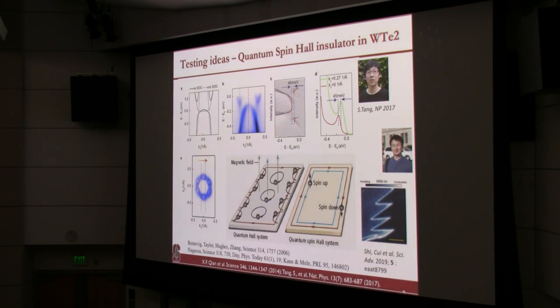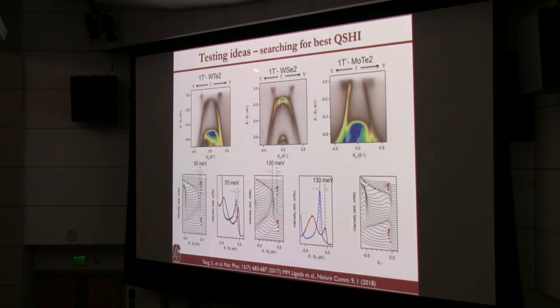Okay. Now, you can also use this spectroscopy to optimize the material. Tungsten ditelluride is a subject being studied a lot. Okay, but if you really look at the system systematically, instead of tungsten ditelluride, you can look at the tungsten diselenide and the molybdenum ditelluride. Okay, by replacing different materials, you realize that tungsten diselenide is probably a better topological material. Okay, it's a much bigger gap. So that means that you can have things at a higher temperature. On the other hand, the molybdenum material, molybdenum ditelluride, will not be the case.